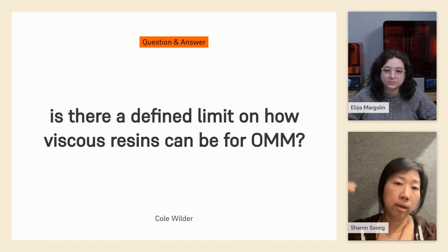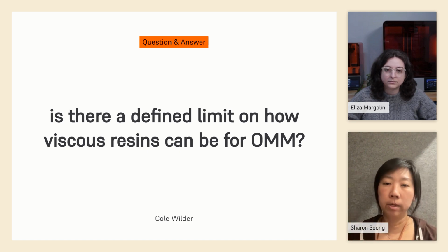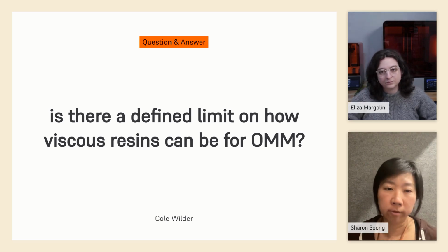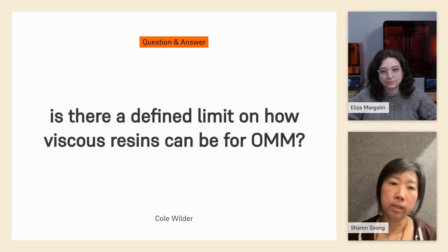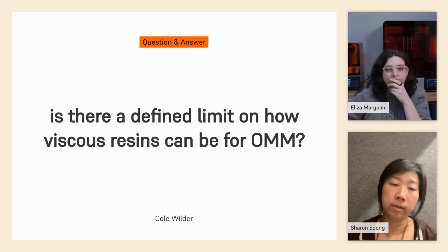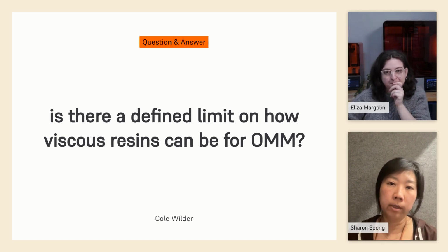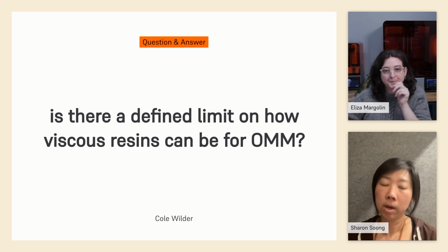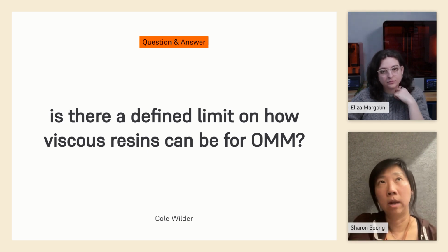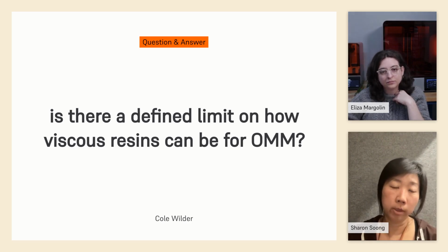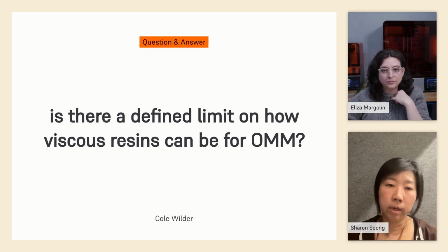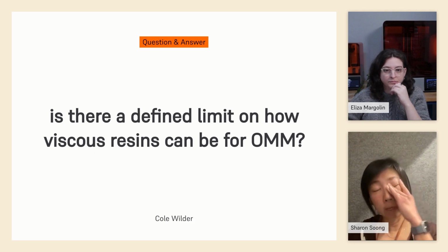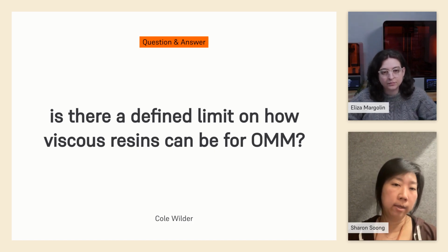There are ways to mitigate the squish move, which is a higher layer height. You're going to have much better pressure if you're doing 200 micron or 150 micron layer height versus a 25 micron layer height. Then obviously your resin has to be tailored so that the light can actually go through whichever layer height you choose. If you can get away with wiping, that will also help with printing viscous resins. Our wiper is pretty robust and can probably move through viscous resin as well. However, the wiping motion with viscous resin often causes trapped bubbles, which could end up in your parts, so you could consider taking that away. We don't have a defined limit. Internally, I think the most viscous resin we ship on Form 4 today is probably around 9,000 centipoise, which is silicone, but that is not the limit of the machine.